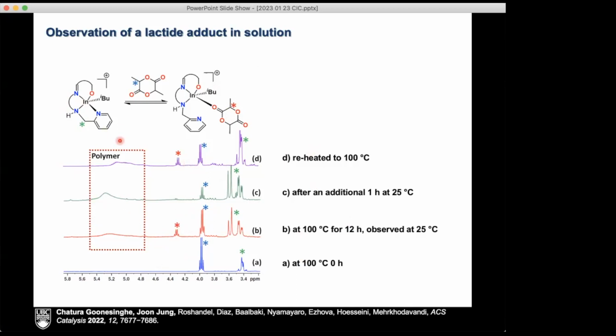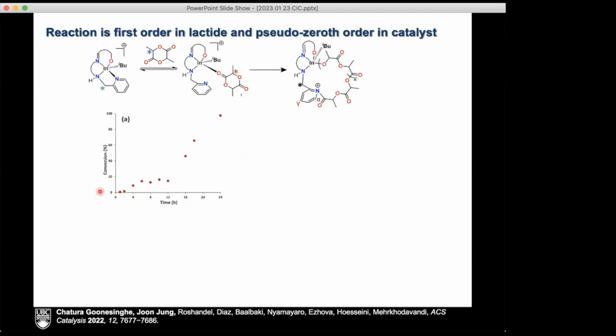At the same time, there's some polymer generated, and we think that that's what's happening. So this is a very stable system, but if you heat the crap out of it at 100 degrees, you're going to be able to form the lactyl species. And then once that forms, the first thing that can happen is the attack of the pyridine on the lactide. And once this forms, then we have an indium alkoxide, which I have shown you earlier that indium alkoxides in our system are very good catalysts for lactide polymerization.